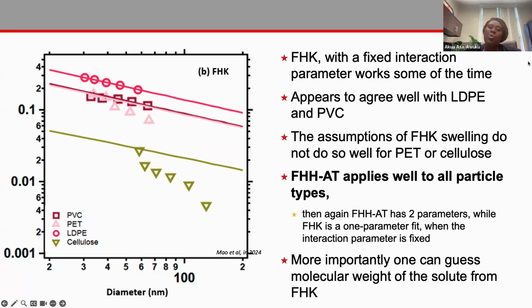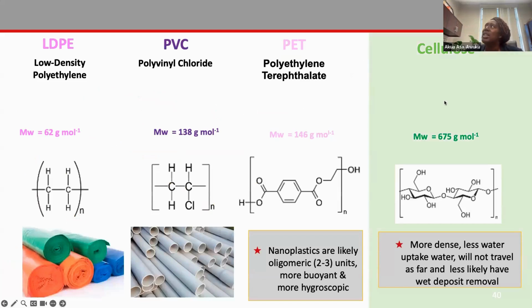But more importantly, what we're able to do with FHK is that we can guess molecular weight from the solute term. So Chuning did that. That is, from the data, you can do essentially a regression that estimates the molecular weight that would produce that kind of hygroscopicity. And so what we find is that for LDPE, the estimated molecular weight is about 62 grams per mole. Why is that important?